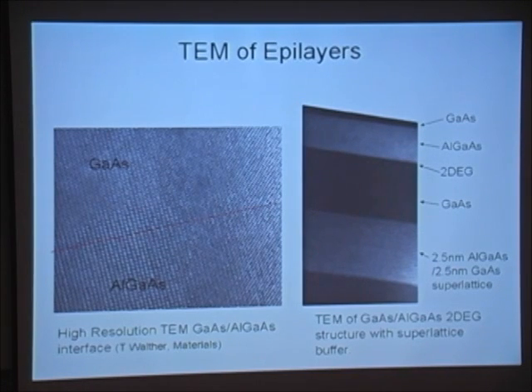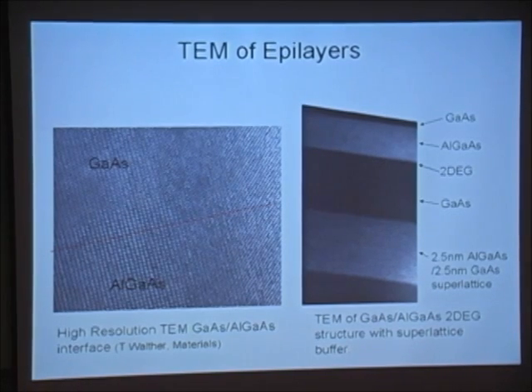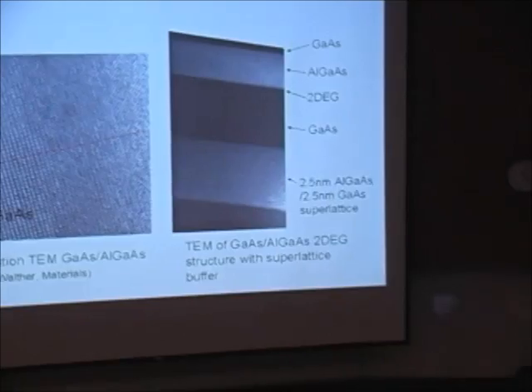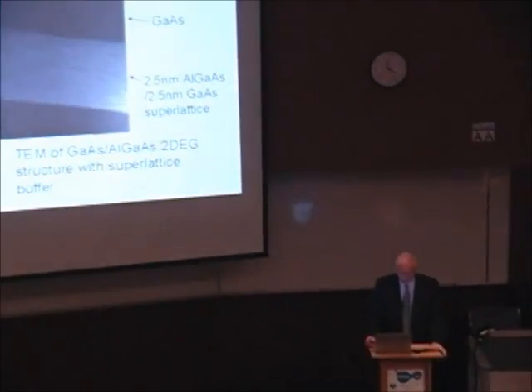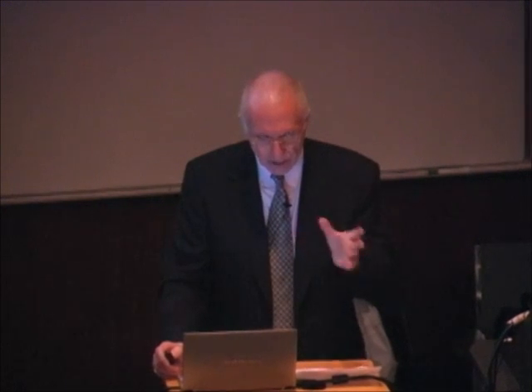And that's the advantage of the system, that the aluminium gallium arsenide and the gallium arsenide are almost perfectly lattice matched. And so there's very little scattering at the interface. And because of this, the mean free path for scattering is very high. And all various types of quantum phenomena can be seen without the complexity of scattering.